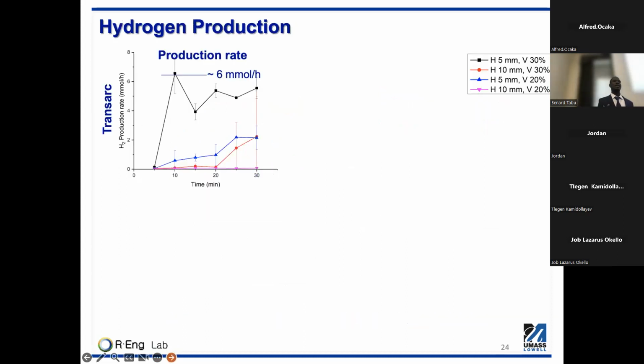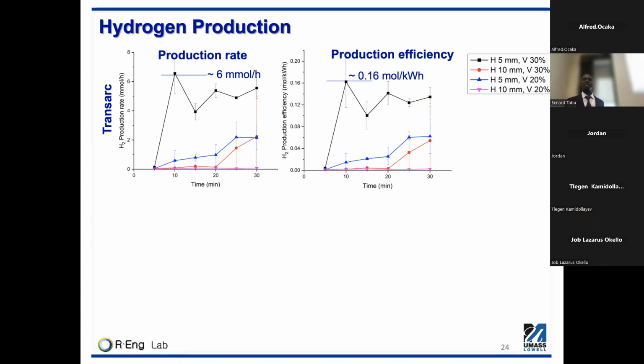So we assess the performance of this reactor for the production of hydrogen using 2 different parameters: hydrogen production rate and hydrogen production efficiency. And this is the hydrogen production rate for the transfer arc. We see that for a higher voltage level of 30 and shorter spacing, the production is significantly higher, and it increases rapidly within the first 15 minutes and tries to level off. And here we have a low production rate, probably because that's the time the feedstock is getting melted, so more energy is spent in melting the feedstock. And the hydrogen production efficiency follows the same trend. It's highest for the higher voltage level and lower spacing.